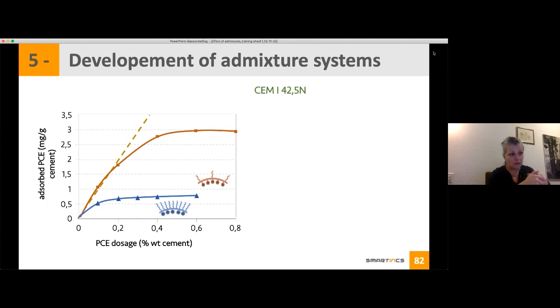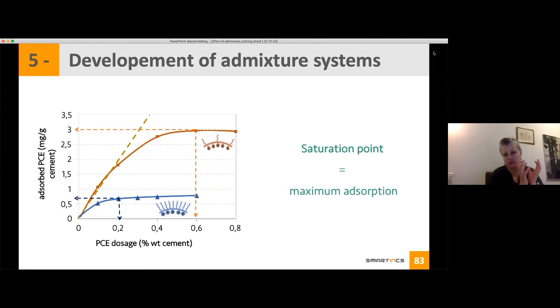But if you look at the red PCE, you see that you can increase until you get the plateau. And then you can determine when you are on the plateau, this is a saturation point. So this is the maximum that can adsorb from your PCE.